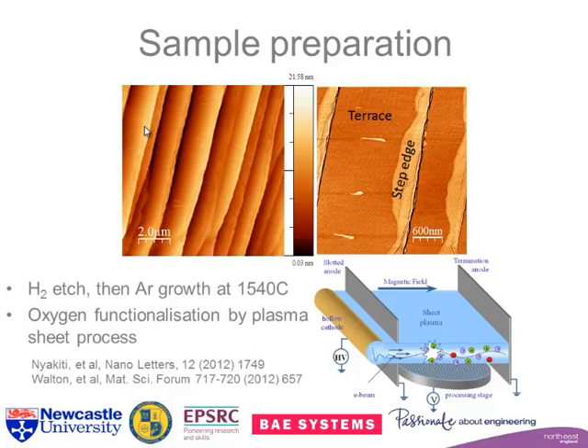And after the growth of the graphene, which in this case is under argon at 1540 degrees, we get a single layer of graphene on the flat bits, and then like the stair carpet at home, we get a couple of layers as we go over the step edge. It's slightly bumped and raised as we go down the steps. All our sensors are fabricated so that they actually look along these terraces. If we go across the step edges, it gets a lot more complicated.